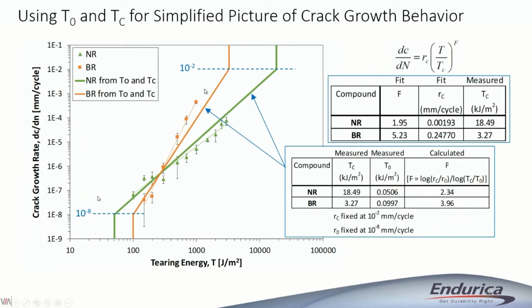Skip ahead here. If you take Robertson's rule and calculate the slopes just based on these assumptions, then these are the calculated slopes that we estimate, right? For the natural rubber, which had an actual slope of about 1.9, we end up with an estimate of 2.3. For the butadiene that had an actual slope of 5, we predicted a slope of 4. Like I say, not perfect, but if you want to measure these things in an hour, let's say you're comparing 10 compounds, this is a very rapid way to make quick estimates and down select on which materials you're going to work with in the long run.